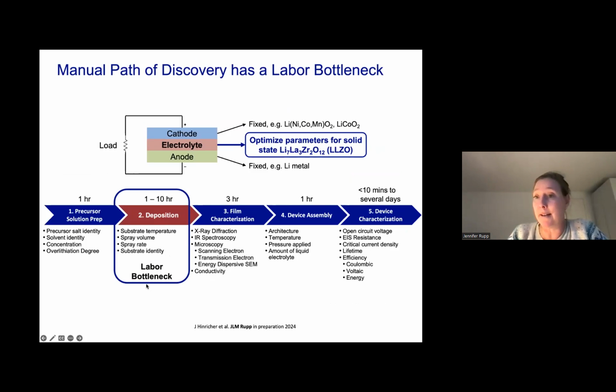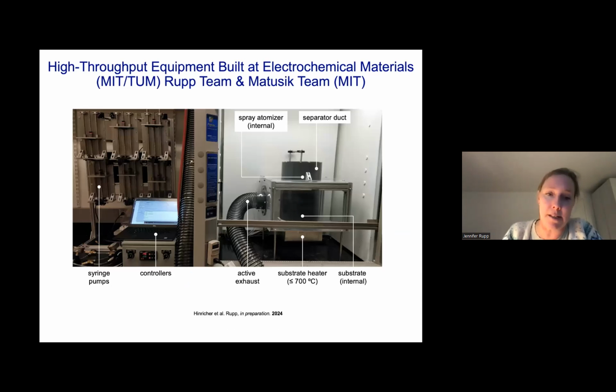Well, the labor bottleneck, for instance, is often really in the synthesis. It is not so much in later doing the characterization. So you can really say it takes about 1 to 10 hours just to do different depositions or any type of ceramic processing. So it makes a lot of sense for us to augment here with high throughput and some degree of automation in the processing. This is what we built. That's, for instance, a sequential deposition synthesis machine that we built together with the mechanical engineering department at MIT and Professor Matusik's team. And the beauty of it is that we have now not one precursor line like I showed before, but we have many.